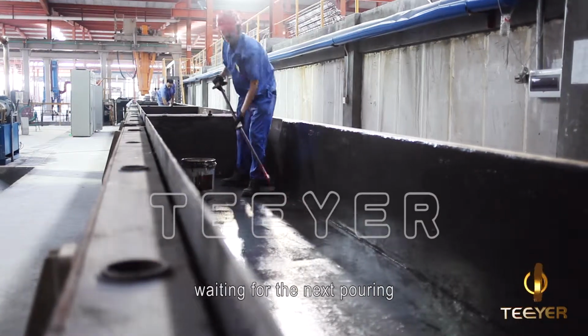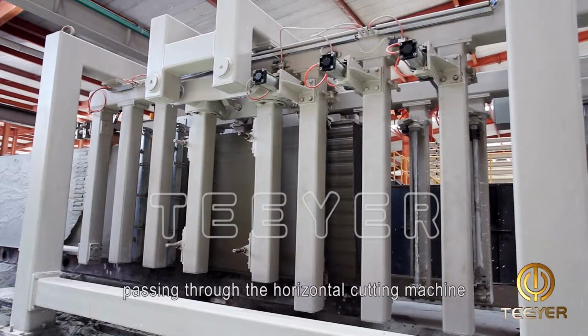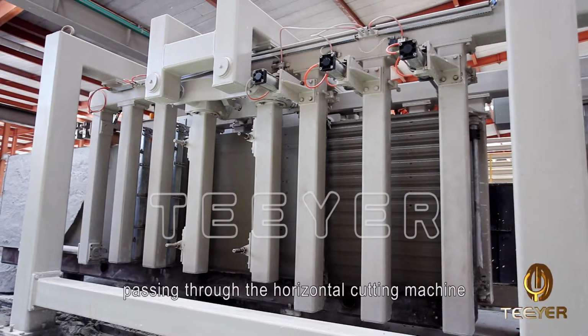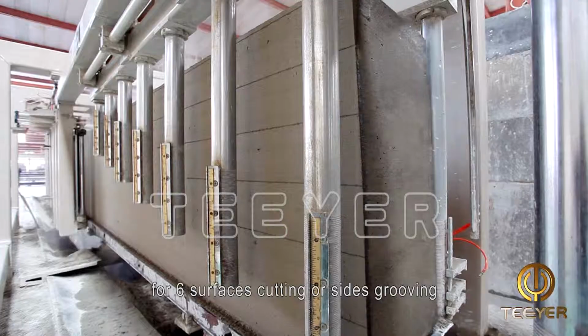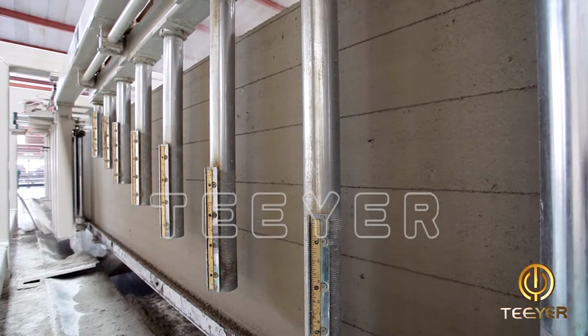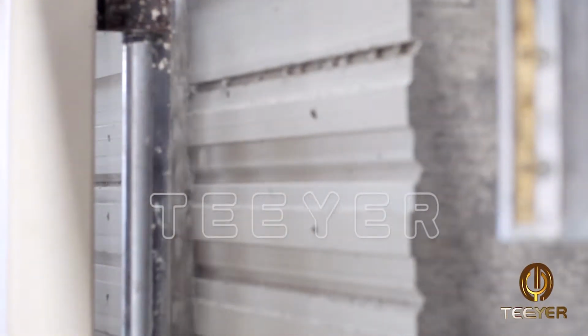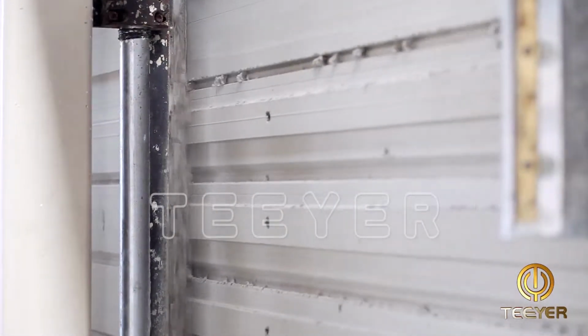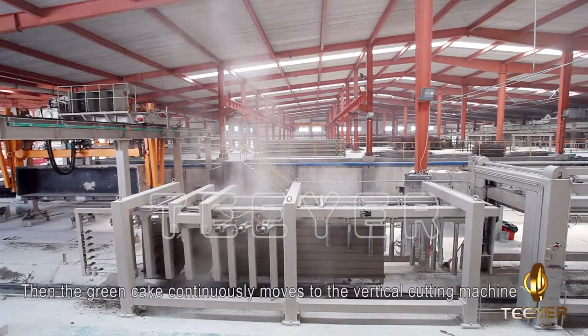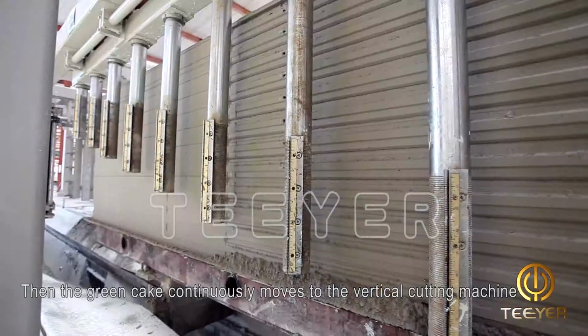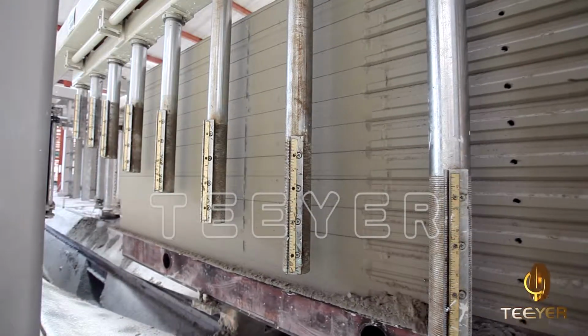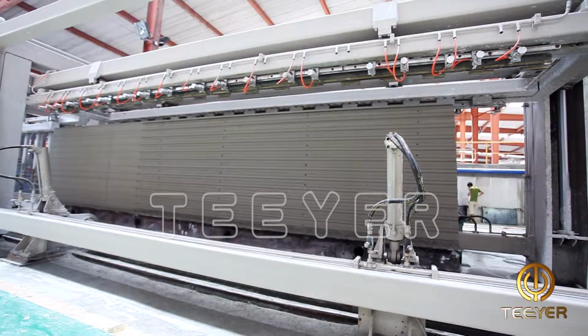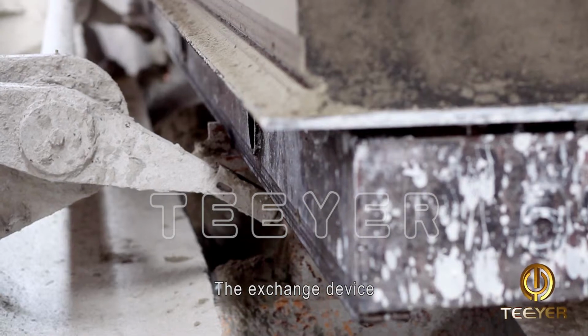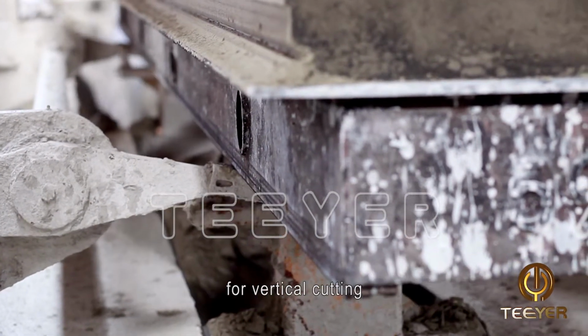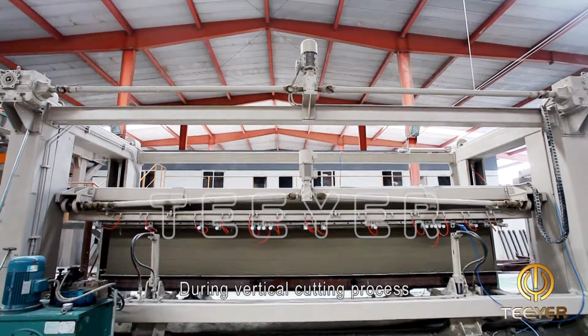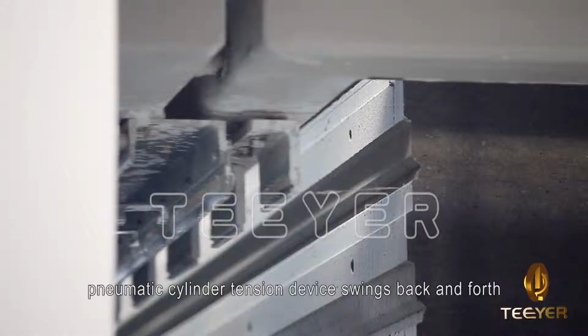The first cutting cart carries the green cake passing through the horizontal cutting machine for 6 surfaces cutting or sides grooving. Then the green cake continuously moves to the vertical cutting machine. The exchange device jacks up the cake as well as the side plate for vertical cutting. During the vertical cutting process, the pneumatic cylinder tension device swings back and forth.